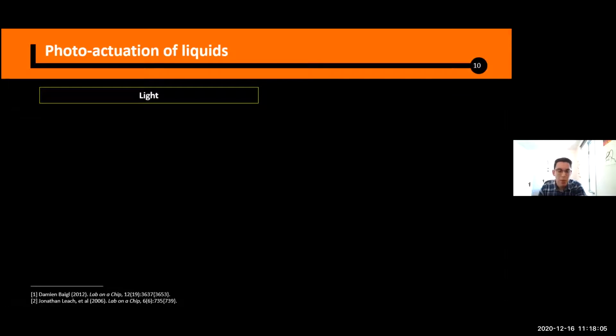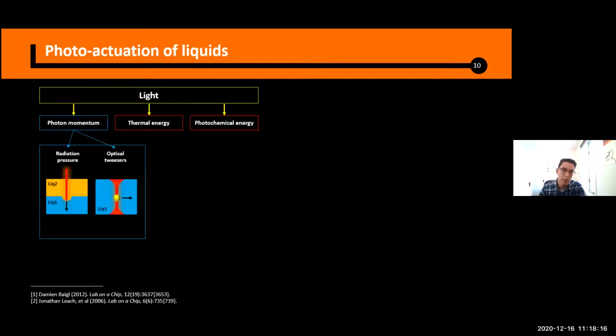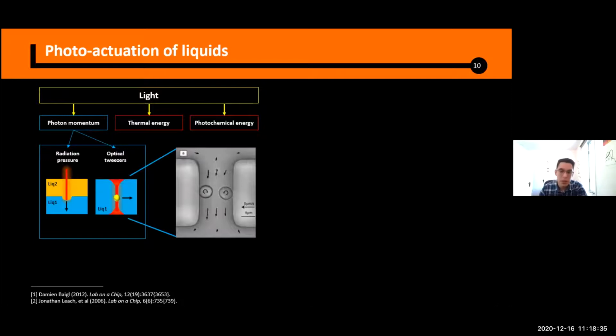And the major works that have been published on this topic have used 3 main strategies to convert light energy into liquid motion. The first one is related to the transfer of photon momentum by radiation pressure to form an interface, as I show here, or by trapping microparticles with optical tweezers, and that can be used as mobile elements to actuate liquids. For instance, a light-driven pump using optical tweezers applied to microfluidics was demonstrated about a decade ago, and here a circularly polarized laser beam induced the rotation of microparticles by transferring the spin angular momentum, leading to a maximum flow rate of about 20 picoliters per minute.